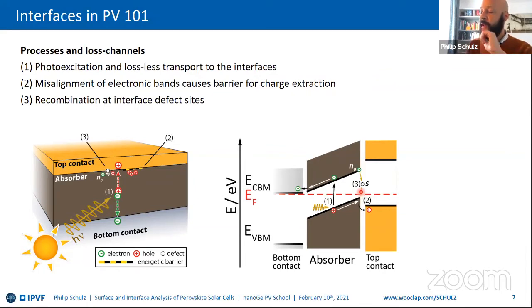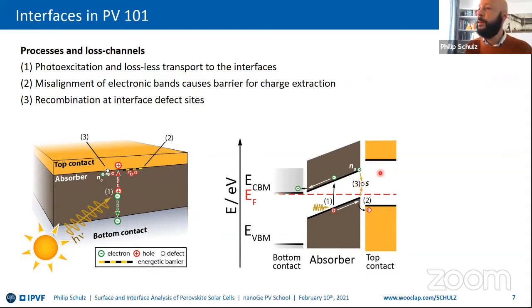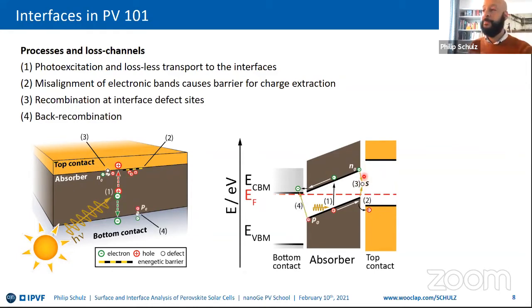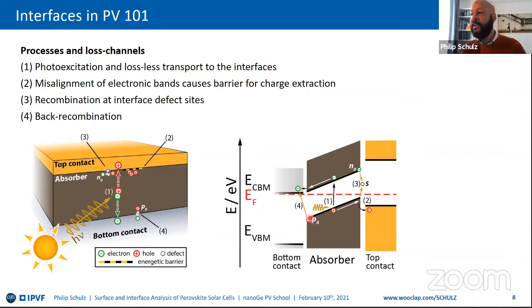The interface is actually the largest defect in a solid-state body. By definition, the 2D dimensionality breaks with the 3D band structure, inducing various defect types — dangling bonds being a classical example in silicon — that can create states in the middle of the gap and therefore act as recombination sites. When carriers of opposite sign reside at the contact interface, which you usually avoid by introducing a blocking layer, you can have back recombination that is detrimental. We will have a more detailed look at this tomorrow in the presentation from Uwe Rau.